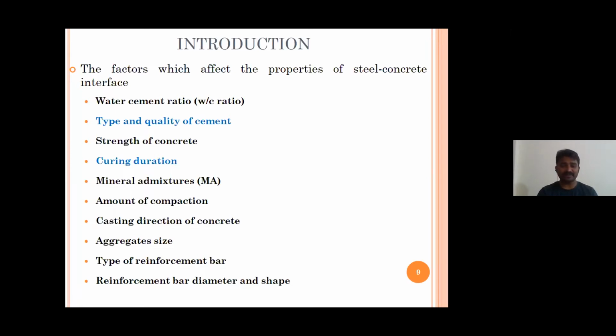The type and quality of cement even affects the properties of the steel concrete interface. Strength of concrete will also affect, M30, M40, M50, and based on that also some studies have been done. Curing duration also affects the properties of the steel concrete interface. Mineral admixtures, amount of compaction, casting direction, aggregate size, all that. So these are the different parameters which will affect. In the present study, we have taken into consideration only two parameters. There are a few other parameters which other researchers have already studied. So in our study, we are only concentrating on type and quality of cement and curing duration.